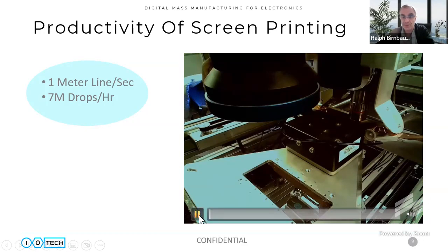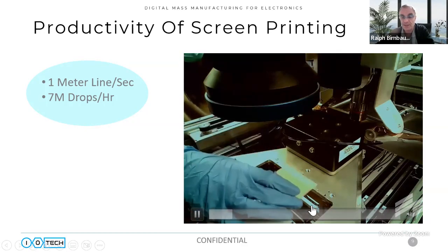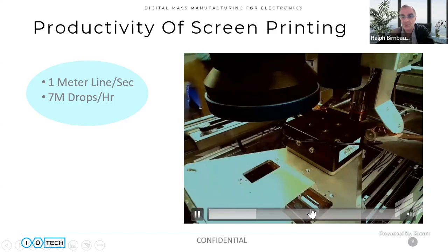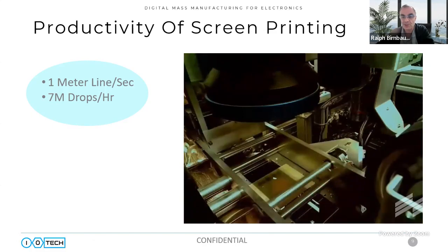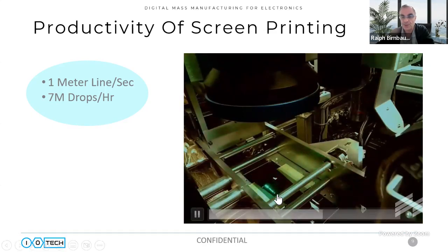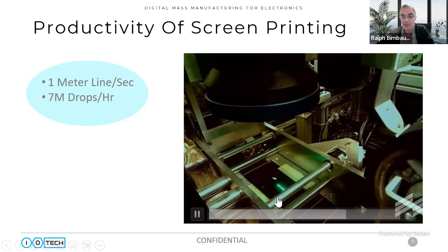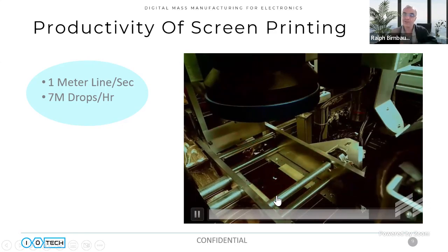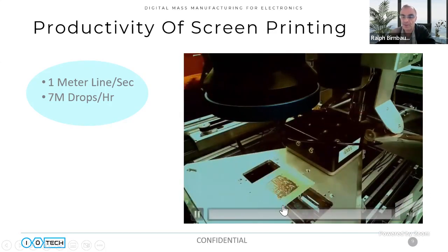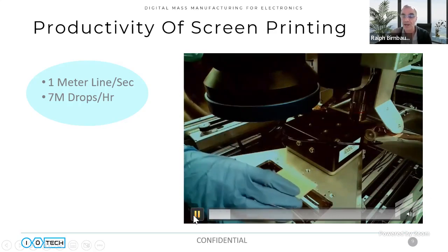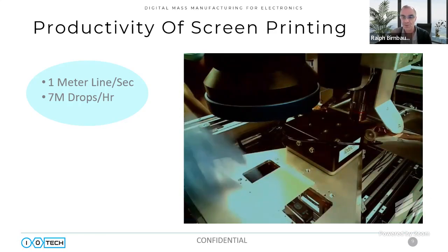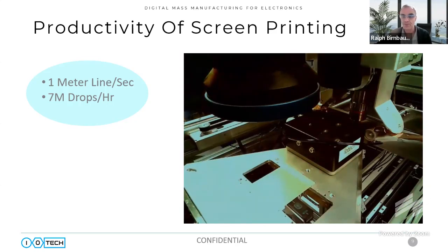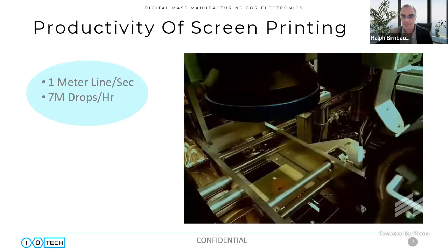To show you in real time, you can see the operator here on the left placing the substrate onto the machine. The printhead will come over the substrate. The material is being deposited onto the carrier film, and the laser goes to work. 1, 2, 3, 4. Printhead moves to the side, and you see one single printed circuit board layer. I like that so much, I'm going to show it to you again. So this is real time. You can see how fast it works. This is, of course, only a small substrate. We can adapt for larger panels, of course, too. That was the material, and that's the laser going to work.